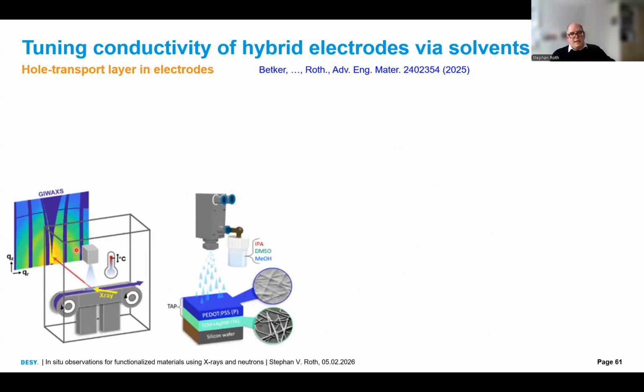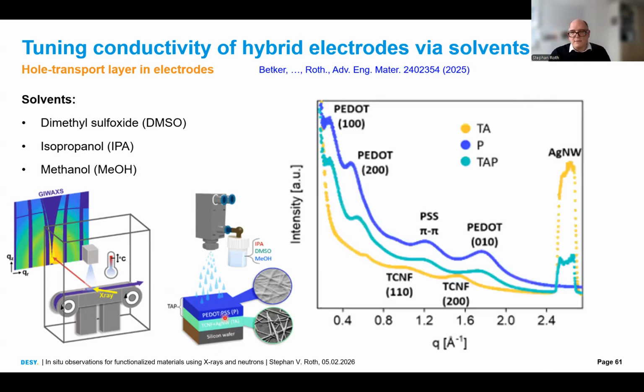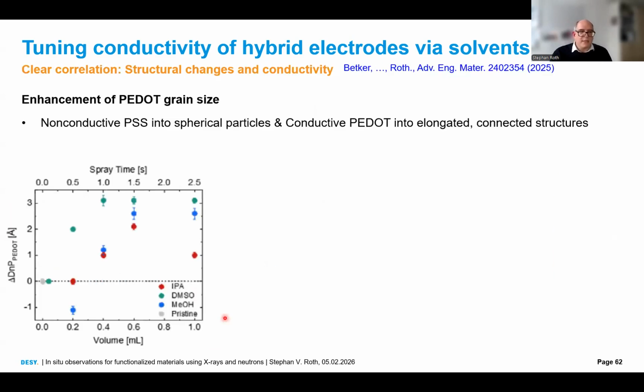And we can then go a step further. We can really then take our PEDOT:PSS on a silver nanowire electrode. This is basically the half cell of a solar cell. And then we spray deposit IPA, DMSO, and methanol as typically used solvents. You see here the roll-to-roll coater, which we really then did in situ with GIWAXS. And we can follow the different crystalline changes here. And especially then we can look what happens in this PEDOT:PSS when we see that its nanostructure changes.